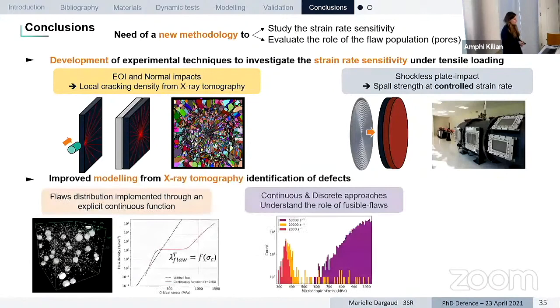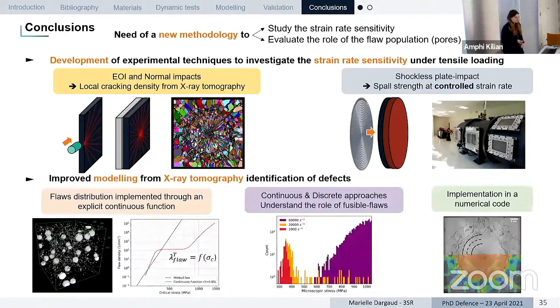We've improved the modeling using X-ray tomography to properly characterize the full distribution of the defects. We've developed a continuous and discrete approach to understand better what is the role of the defects. And we were able to implement this continuous description into numerical codes to predict the fragmentation of the material.